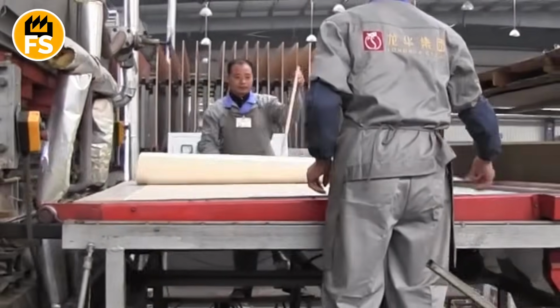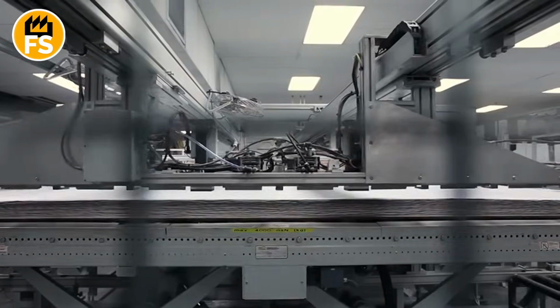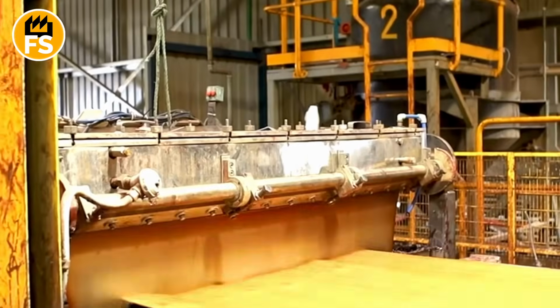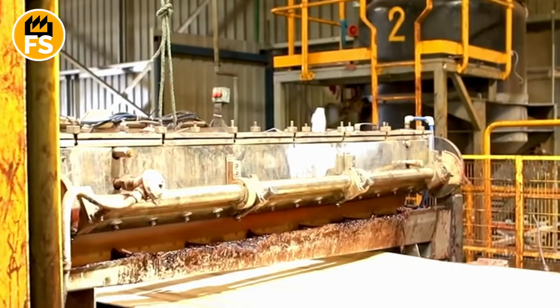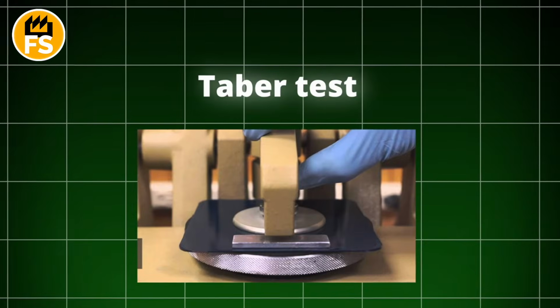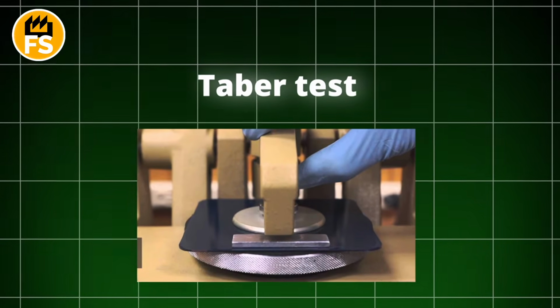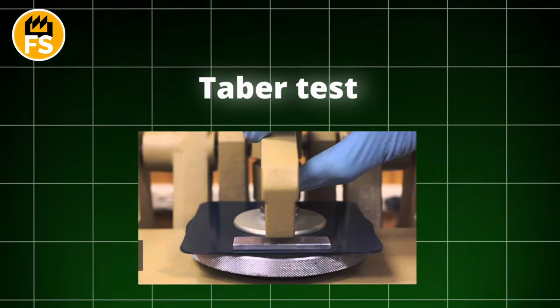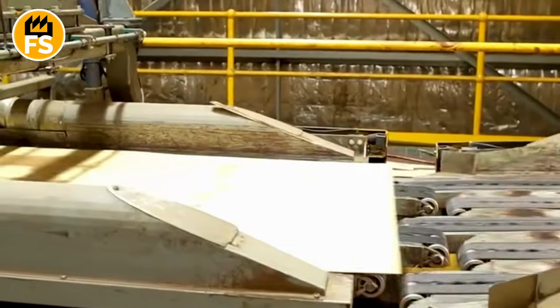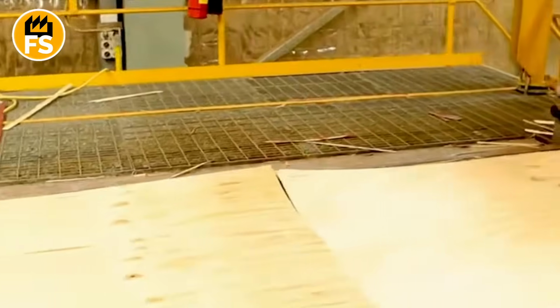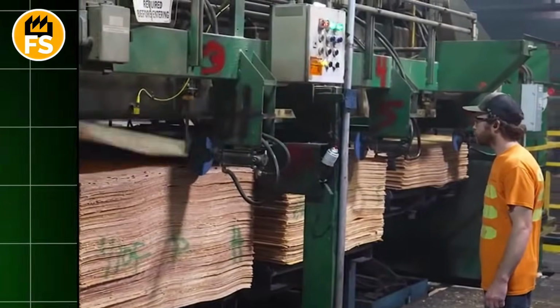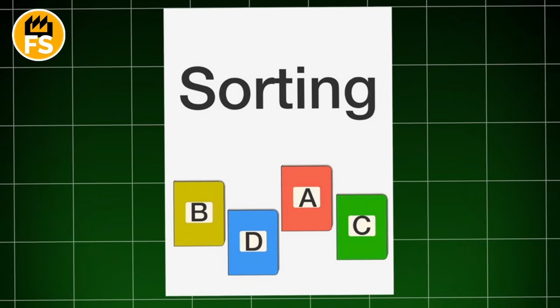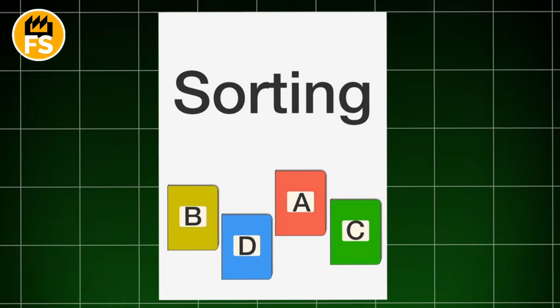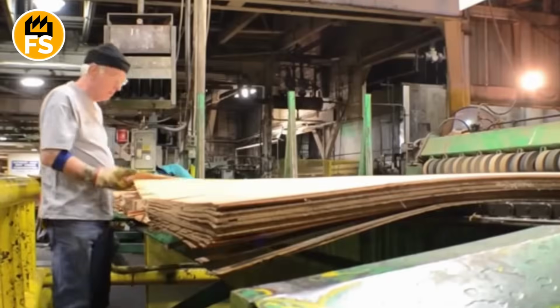The final stages of production include quality control and packaging. Each batch of laminate is tested for abrasion resistance, impact resistance, moisture resistance, and other parameters. The abrasion resistance test, known as the Taber test, determines the wear class of the laminate. A high class means that the laminate will withstand a greater number of abrasion cycles. After successfully passing all tests, the panels are sorted, packed in sturdy cardboard boxes, and prepared for shipment.